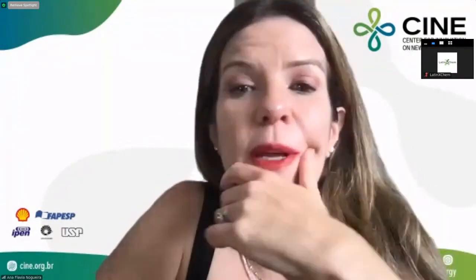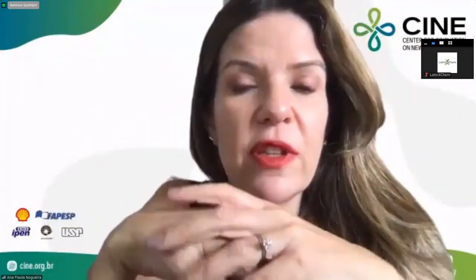Well, people are actually putting everything in the perovskites, from quantum dots to polymers and graphene. In my experience, we have a paper on graphene. We put some graphene oxide in the precursor solution, then reduce the graphene oxide, and it affects the crystallization. Everything that you put in there is going to affect the crystallization, and it's really hard to predict what's going to happen. In the case of graphene, we observed a decrease in efficiency, because you are somehow disrupting the 3D network, but we have an increase in stability. It's much more stable when you have the perovskite with the graphene.